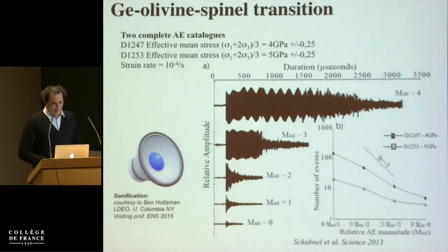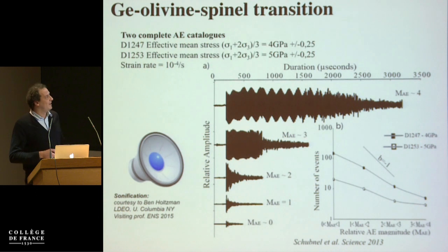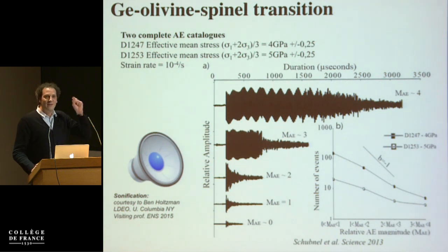So initially what we did, we looked at the large acoustic emissions and the small acoustic emissions, and we figured out that they followed the Gutenberg-Richter law, and we said, okay, it follows the Gutenberg-Richter law even on a small sample like this. So what you hear now is a sonification of those small laboratory earthquakes. But in fact, we were lucky that on one channel we did have a continuous record.